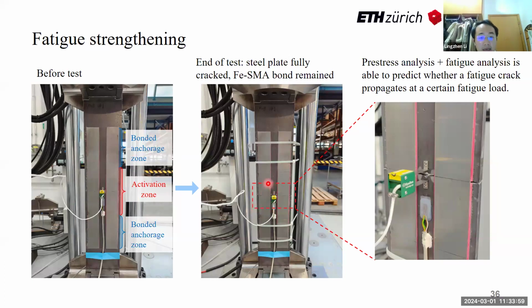Here is the end of the fatigue test. The steel plate was fully cracked. A crack went through the cross section here, but we see that 4 Fe-SMA strips remain holding substantial tensile force and linking the 2 cracked parts of the steel plate.